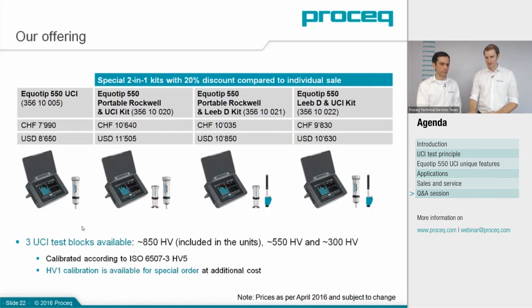Maybe to add here, the test blocks are calibrated according to the ISO standard for Vickers and are calibrated in HV5. But we also offer additional HV1 calibration. If a customer is using his probe mainly with HV1, then we recommend also to have HV1 calibration on the test block. But default calibration is HV5. Fantastic. So the test blocks are also traceable, basically, as you say. Yes, they are calibrated by a traceable facility.